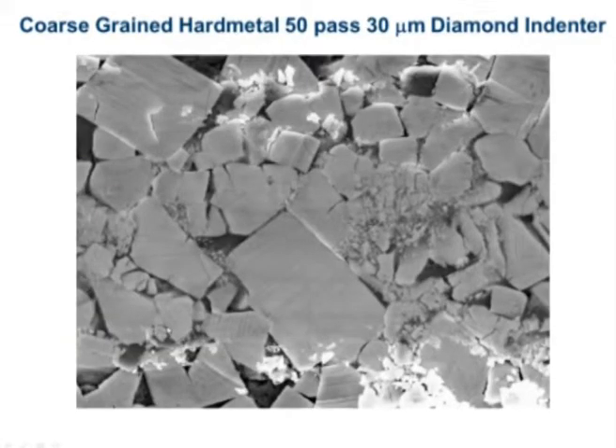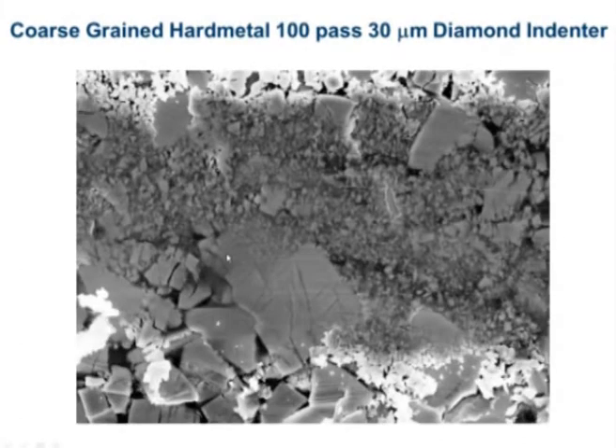I'd like you to look at two micrographs now. This shows another scratch test. Here we've got 50 passes of 30 micron diamond indenter, and focus on this grain here. You can also see fragmentation, fracture, as I was saying earlier. This is actually plastic deformation here, and that's a very important mechanism for this material, and plastic deformation here as well. And if you look at the next slide, it's exactly the same area, and this is becoming an important area.